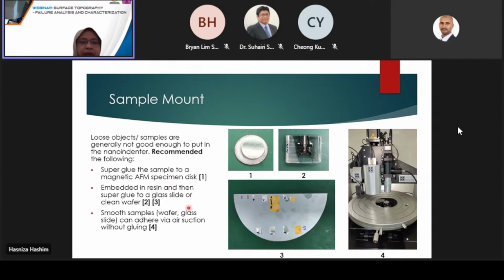Obviously, after that, you need to use some sort of super glue to fix your sample on your magnetic metal disc or on your clean surface or clean wafer. However, please take into consideration that once we apply the super glue, the sample cannot be used for other testing anymore, because super glue is very hard to remove from the metal plate, the glass slide, or the wafers that we put the samples on.